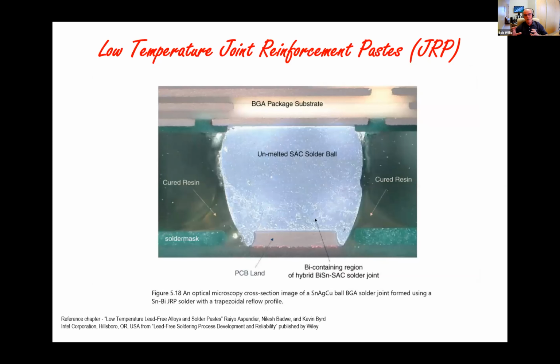So this microsection was taken again as an image from the book that I referred to, and it's not as clear, but on the image you can see the cured resin at the side. Now I've added in a couple of lines here, yellow lines, just to highlight it. So basically what we're doing is we're soldering to the board, and then we're using epoxy technology to hold the joint to the board. So what this does is improve and overcome some of the disadvantages of the material not being as ductile as other solders. It potentially can be used to overcome mismatch expansion, but probably more likely the benefit is overcoming the issues associated with mechanical handling, which is all down to ductility and ductility failures that we mentioned previously.